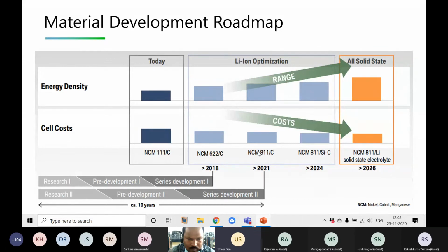From there, we have almost reached 811. There are a few companies who are already commercializing NMC 811. You can see that gradually we are decreasing the cobalt content and increasing the nickel content. Cobalt is the costliest, and that is the reason we are reducing the cost. And if we increase the amount of nickel, the capacity is going to increase, so we can increase the range or the energy density. But again, as I told you, if we increase more and more nickel, then the stability, cycle life, and harsh operating conditions are going to be hampered.